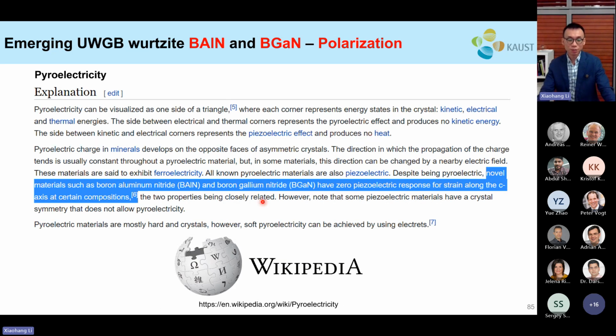Our work has also been cited in Wikipedia. So the spontaneous polarization is actually part of the pyroelectricity of the material, which is common in materials with asymmetric lattice. But I think our work was the first one that showed that pyroelectric materials such as BAlN and BGaN can have a zero piezoelectric coefficient, or zero piezoelectric response, for strain along the C-axis at a certain composition, as I showed you earlier.